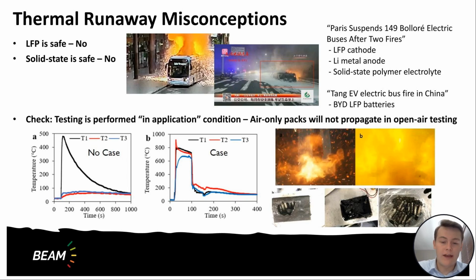I think the key factor in stating the 60 to 70% of the energy output is because of the electrolyte combustion. Well, the electrolytes are somewhat similar, and so you do still have during LFP thermal runaway a massive output of energy. It may be higher to get to that threshold, but there's no doubt that LFP batteries have had major problems in the field in terms of thermal runaway and thermal runaway propagation. A good example is the recent EV bus fire in China that employed BYD LFP cells.